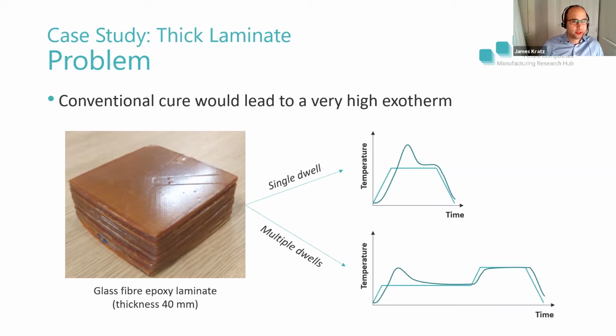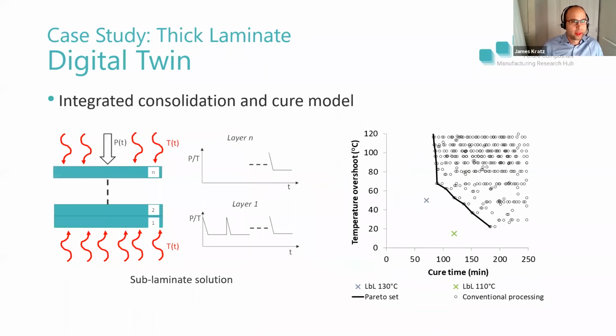So what we need to be able to do, or what we're hoping to be able to do, is to intensify the process and save time as well. The way we looked at that with layer by layer curing is we started by creating a digital twin of our process. We broke the laminate down into a series of sublaminates, where the first layer would see the pressure and temperature of the entire process, but the final layer, layer N, would only see one temperature and pressure cycle.